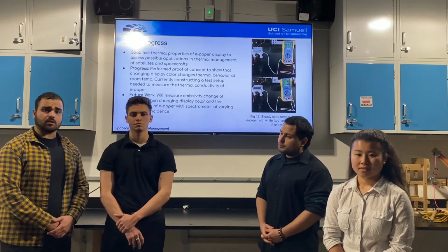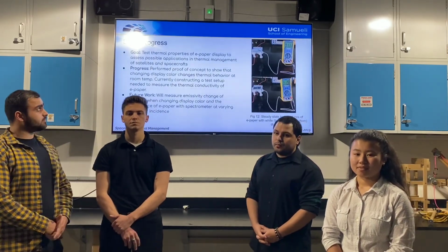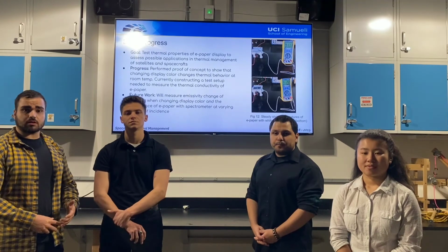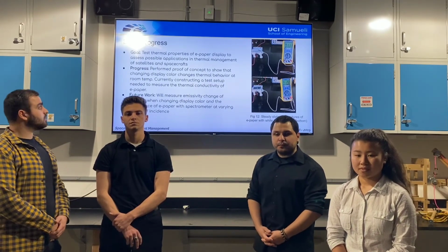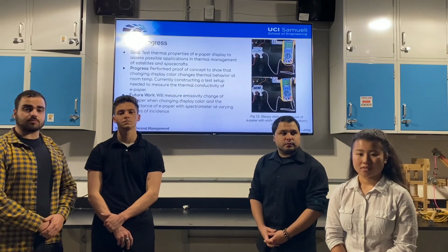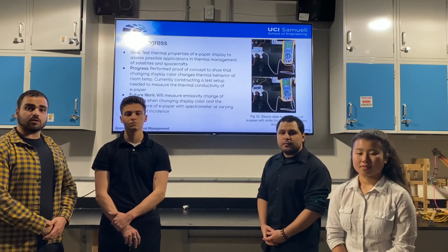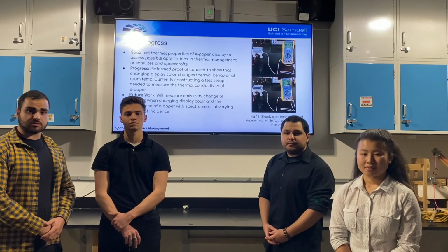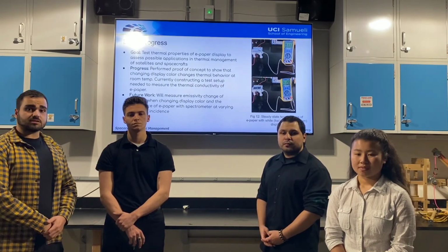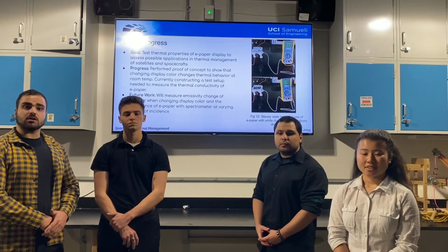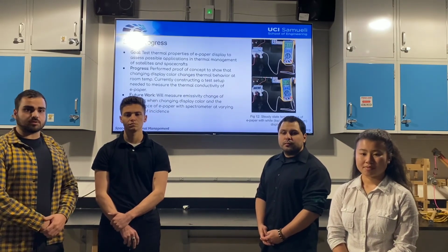For the E team, our goal is to test the thermal properties of the e-paper displays to assess whether they are a good alternative to conventional PEDs. So far, we have tested the e-paper using a proof of concept test where we found a 5-degree Fahrenheit difference in temperature based off different display settings. This suggests that there is an emissivity change when changing the display setting.